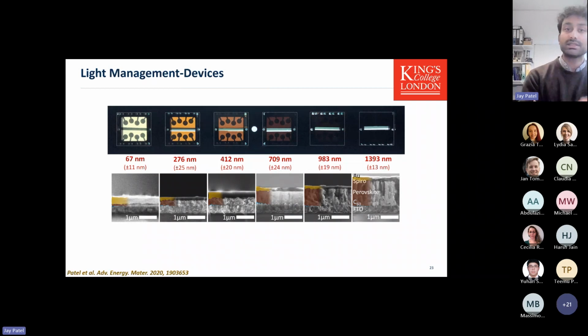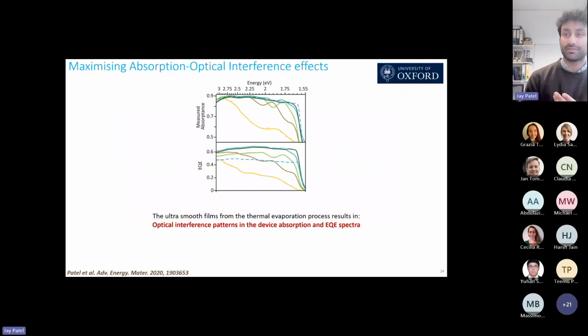I'd like to reiterate that this is a single junction device. We are not going into multi-junction yet because we're just trying to explore the properties of a single junction device. I made a whole range of different devices with different thicknesses, and you can see here that the technique really does allow us to control the thickness of the material quite precisely, which is important to make sure that we can absorb the maximum amount of light in a solar cell. What else we found using this technique is that when you create these thin films, you start to see an interference effect. And this is well known in thin film optics.